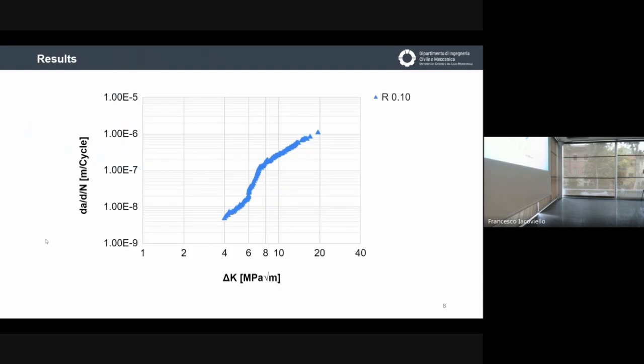So this is the first result. You can see that in terms of threshold it is not so good. In megapascal root meter it is not so high. Then you have the first stage, the second stage, third stage, and so on. This stage seems to be linear in this scale. This linear range could be the highest one, but the slope is not the same. And here we have another region that is linear.